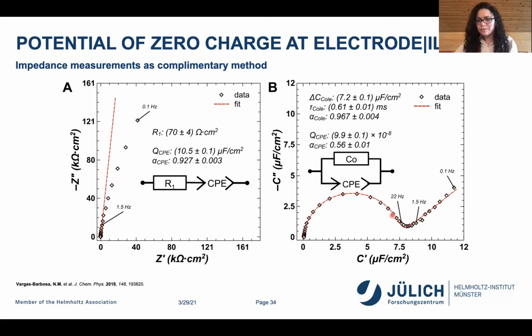Where the delta C Cole gives you the diameter of the semicircle. You get a time constant for the Cole element, which is extracted from this maximum over here. And you also get an alpha parameter, which is telling you about the ideality. How ideal is this semicircle? 1 is completely ideal, less than 1 is less ideality.